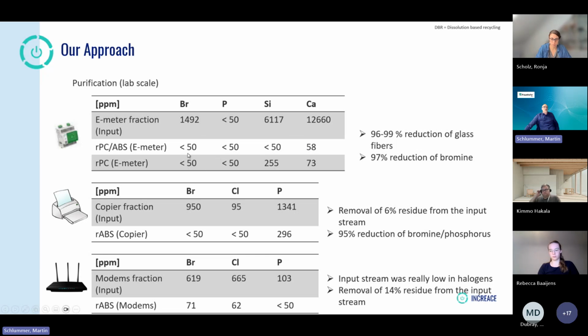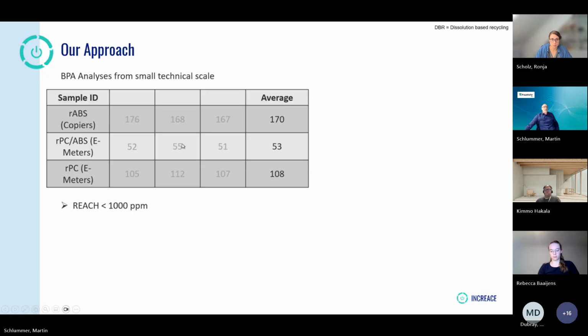This refers both to the flame retardants on the one hand and also to the fillers, meaning if we apply the fine filtration as we did, we can get these fillers out of the feedstock. You see that the reduction rates are quite significant for all the reported ones. For the modems here, this is just indicating it is possible. You see a factor of 10 more or less. We know from other publications and other studies that a stepwise further reduction can even go to a 99% reduction. But these are the typical contaminants.